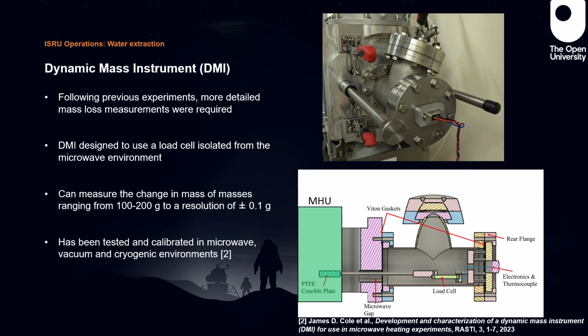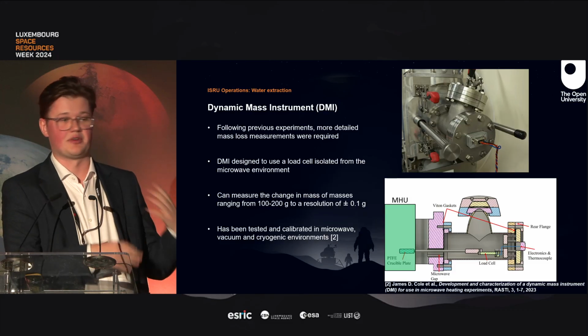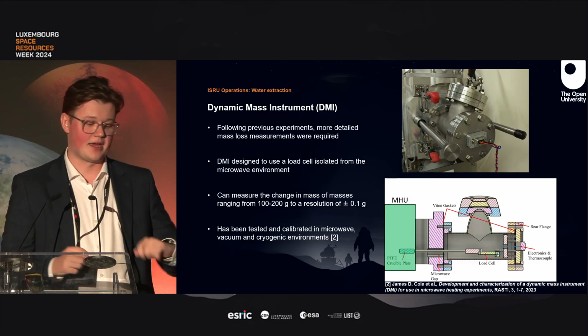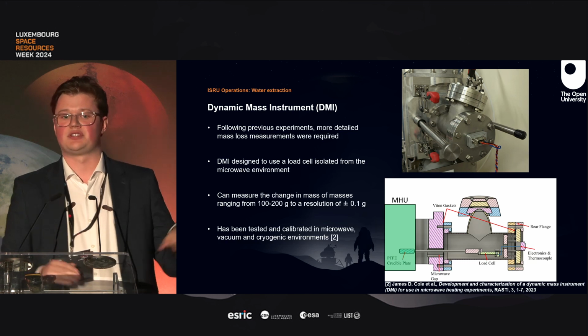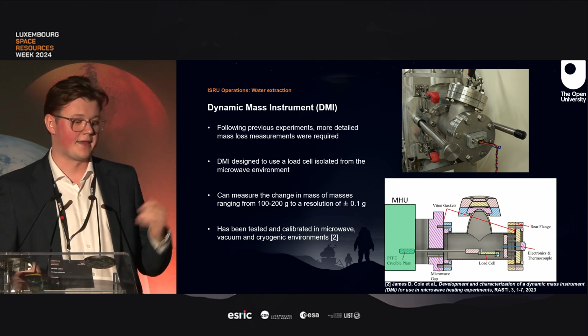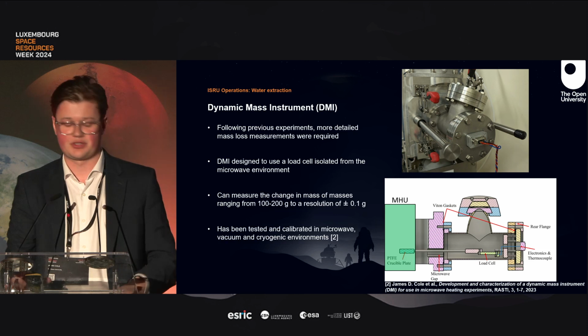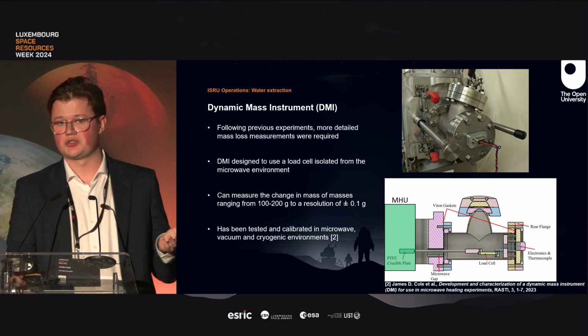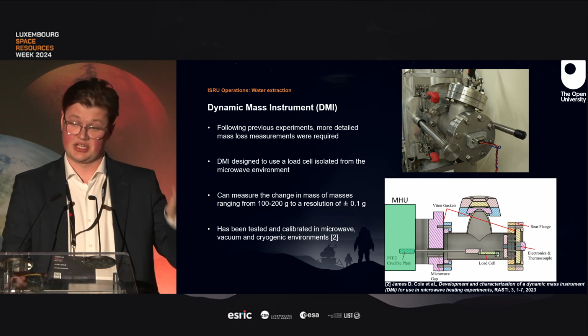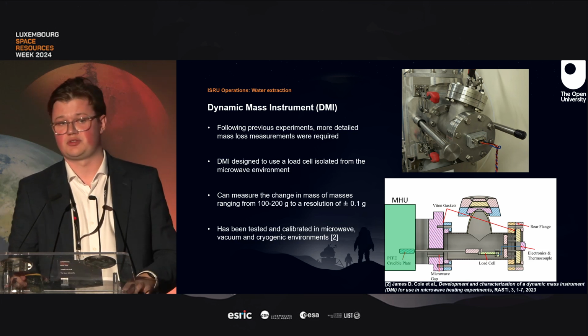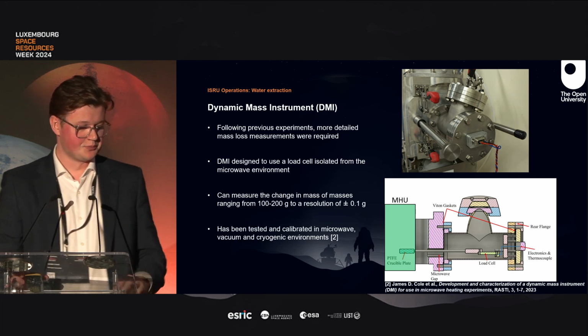in the microwave environment. So how it works is a load cell measures the mass, but it is isolated from the microwave energy, so there's no interference going on. And then a load arm is used to go into the cavity, which a sample is placed on top of, and that can be used to measure the mass in real time. So we can measure samples between 100 and 200 grams, their changing mass, I should say, with a resolution of plus or minus 0.1 grams.